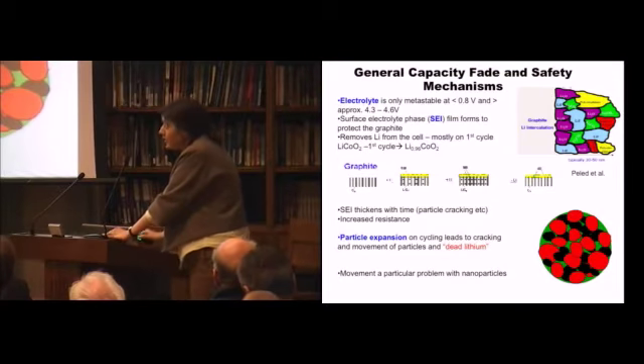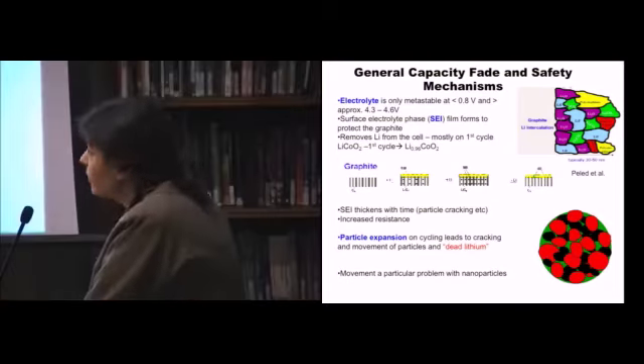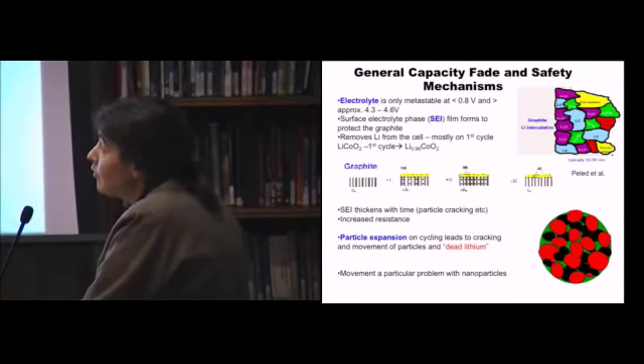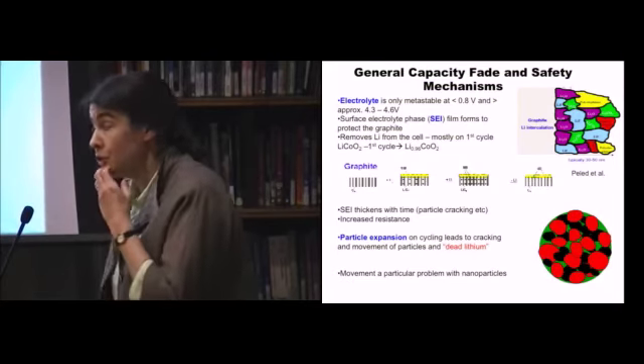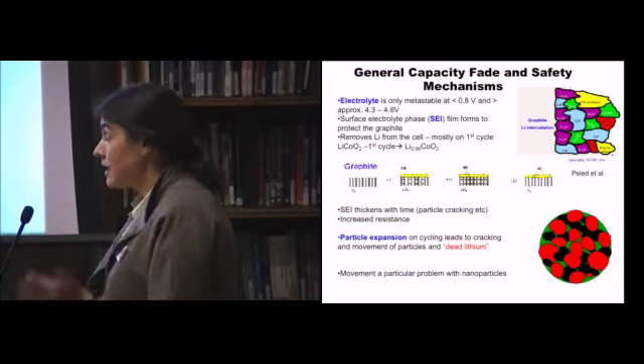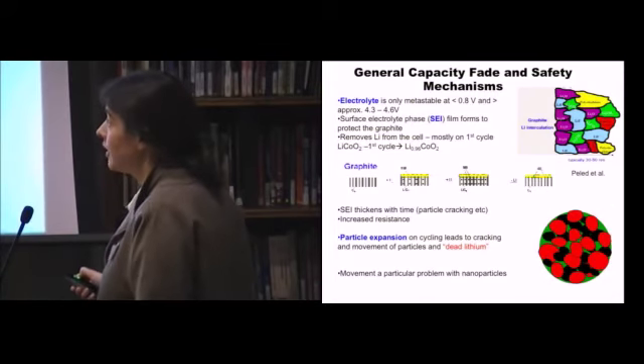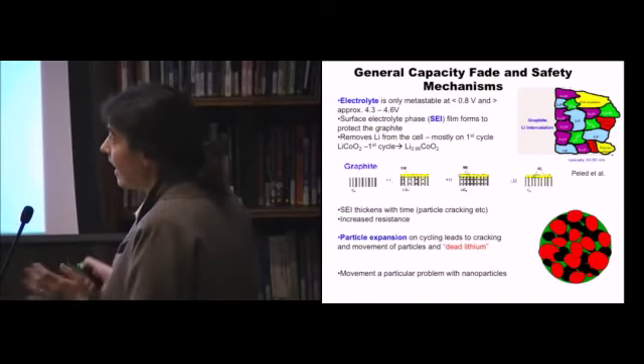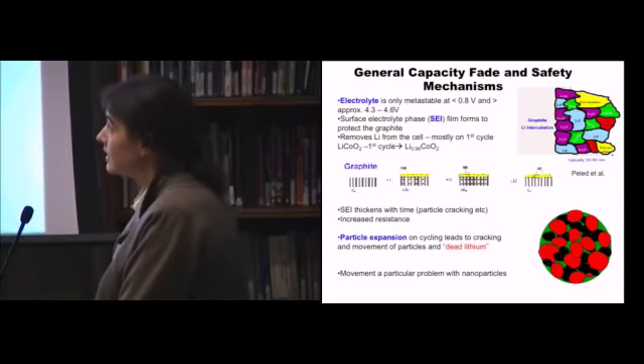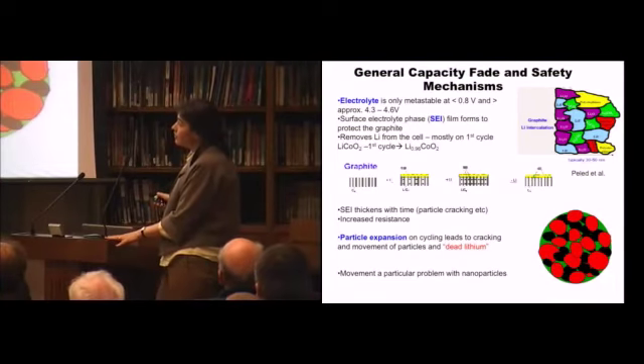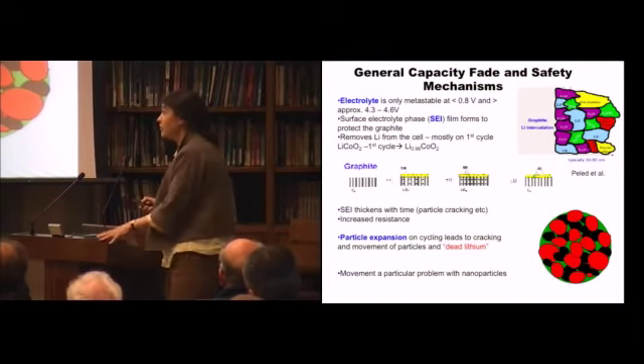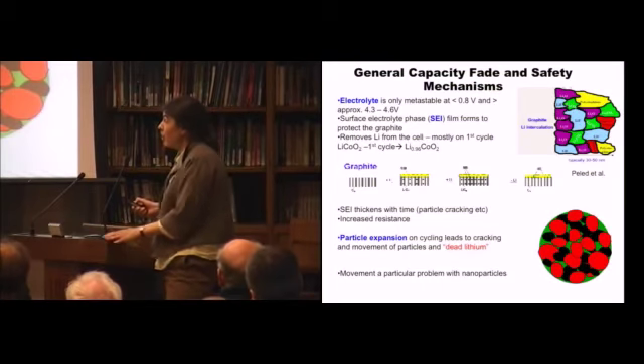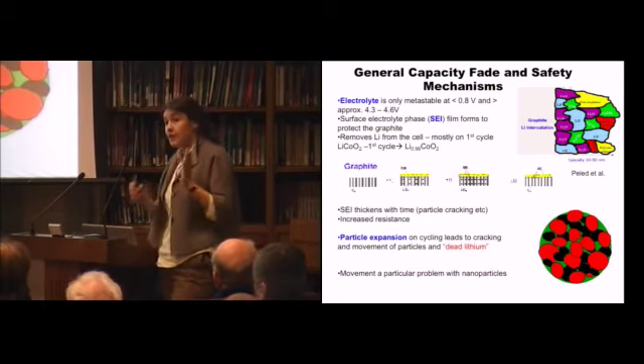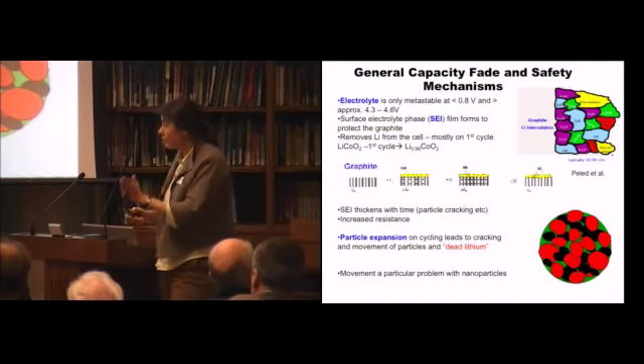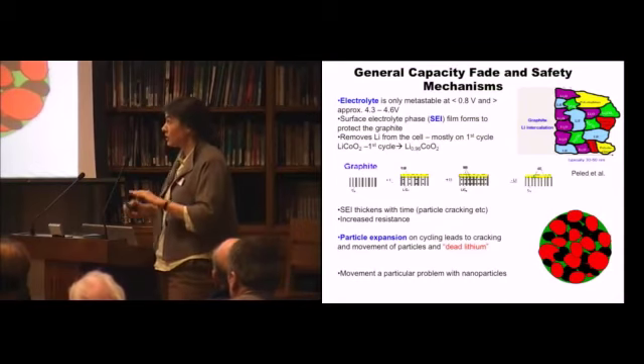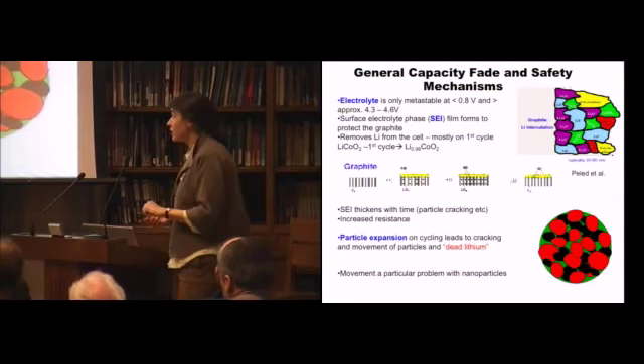So it turns out that the electrolyte, so it's a carbonate electrolyte, isn't stable. So it's not stable below 0.8 volts, and it's not stable above 4.3 volts. And so what battery manufacturers do when they make a battery is they cycle it once, and some of the electrolyte then decomposes to form this so-called solid electrolyte interphase. And so this SEI coats the graphite, forming a passivating layer, preventing further reaction. And this reaction involves decomposition of the electrolyte, but will consume some of the lithium. So you'll lose between 1 and 2% of lithium on that first cycle. And there's a finite amount of lithium in your material. The only lithium you have is in the original amount in the electrolyte and the original amount in the lithium cobalt oxide. So any side reaction takes away lithium and results in capacity loss.